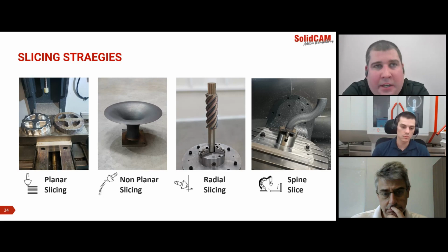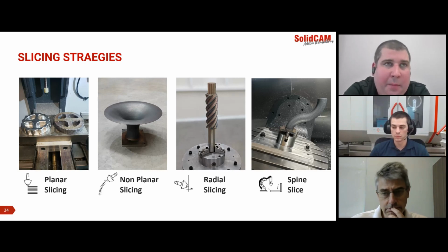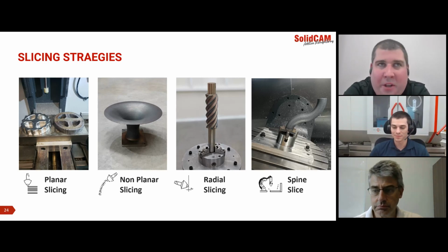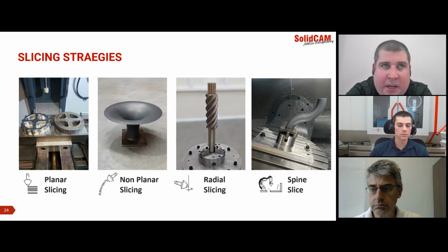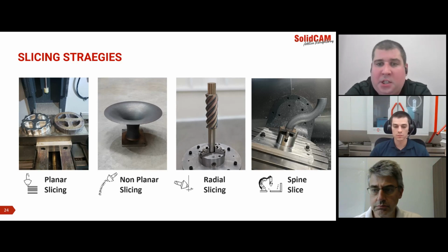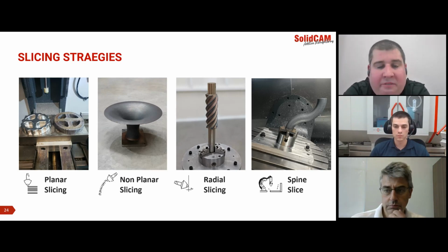And by tuning this minimum and maximum, knowing what the process can handle, there is a physical limit. We're not going to be able to print a 4 millimeter, 5 millimeter tall layer height. So there is a finite layer height that you can't violate. Normally our nominal layer height for single wall is around 0.5 millimeter. For solids, it's about 1 millimeter. We can go a little bit lower than that. When we're doing a spine slice, we can handle about a quarter of a millimeter, about 0.010 of an inch, up to about 1.5 millimeter.